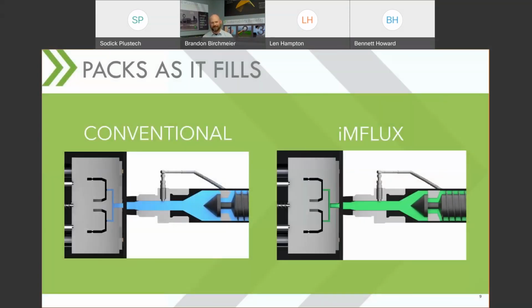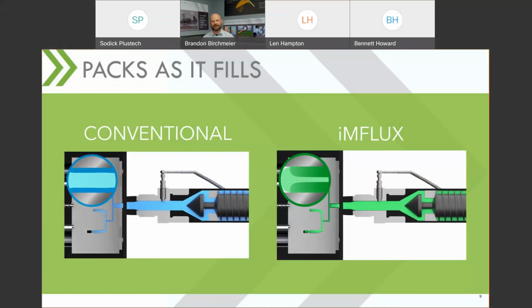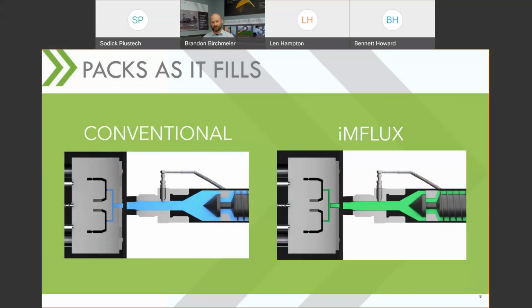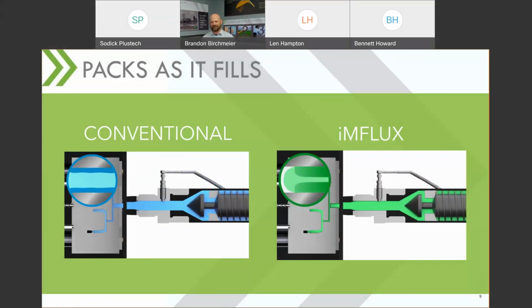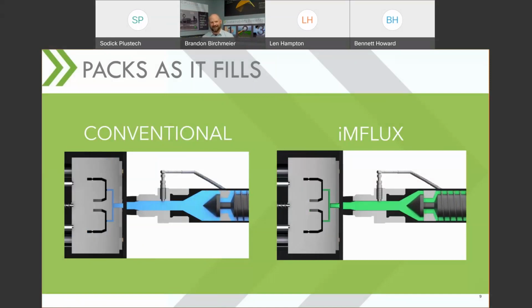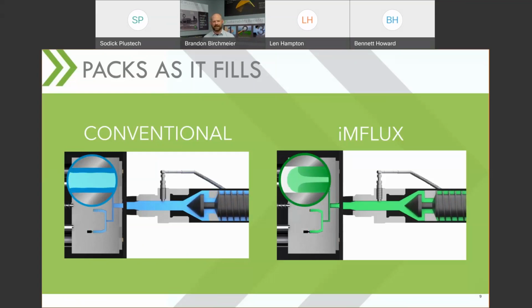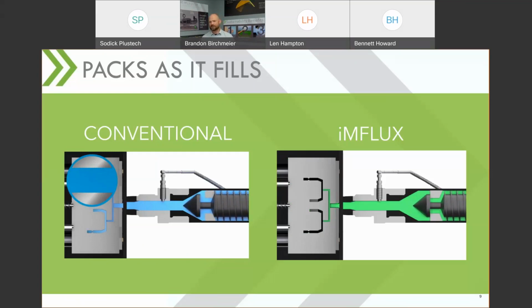How does this work? So we got this neat animation that kind of demonstrates this for you. On the left is your conventional process. And what I want you to recognize is what happens at transfer. And this is important. So as you're skinning your layer of polymer across the cold mold steel, as you'll see in the animation, you're getting this skinning. And once you transfer and you get a little bit of screw bounce or something, there's a relaxation of that thin wall section, that thin area, that skinned area, and then it's reapplied to the surface. So if you deal with things like hologramming, tiger striping, things like that, it's coming from the fill and transfer portion of your process, where you're applying the plastic to the surface of the mold, allowing it to relax and then repressurize.